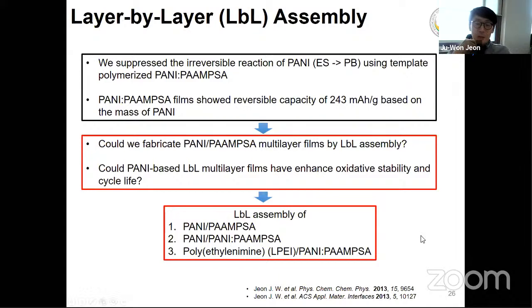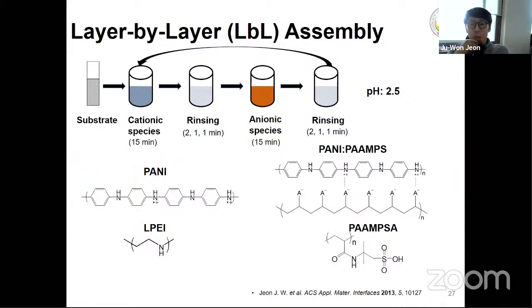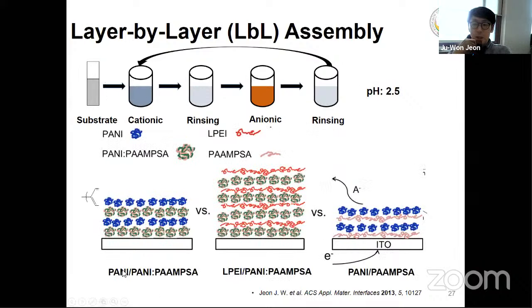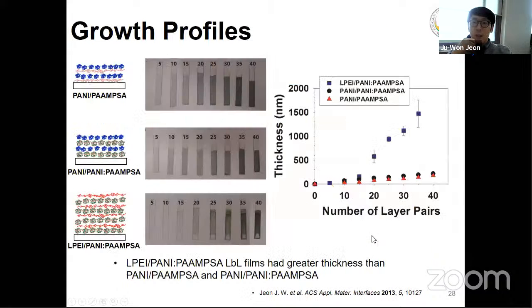To answer this question, we built up three different layer by layer films. These are the polycations that we used, and these are the chemical structures of the polyanion that we used, and we repeat this LBL process and build up these three different multilayer films. As you can see, the film became darker and darker with the increasing number of layer pairs, which means the film is growing very well.